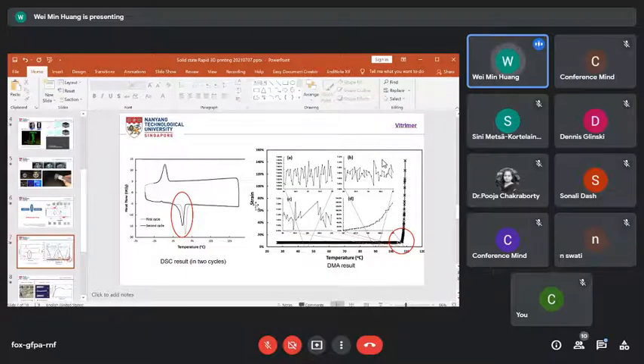because we use this kind of cyclical loading with a very tiny force applied on it. So you can find that if we heat up to over here, 45 degrees, the material is pretty elastic. Even if we heat up to over here, 90 degrees, this material is still elastic. It doesn't flow, okay? Because of gravity, there isn't any such flow event. So the material actually is pretty strong.